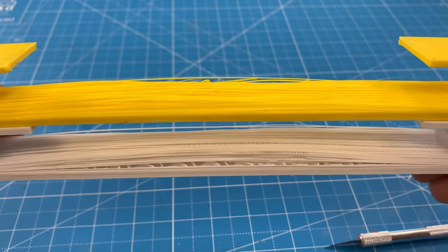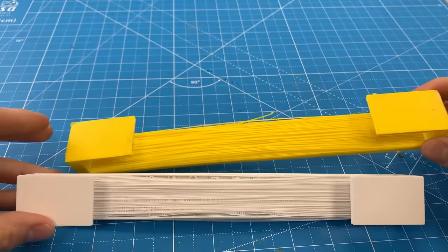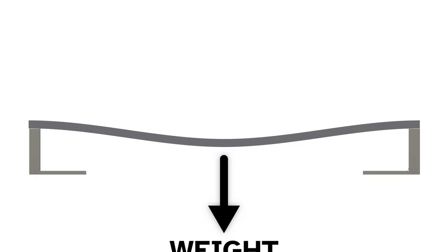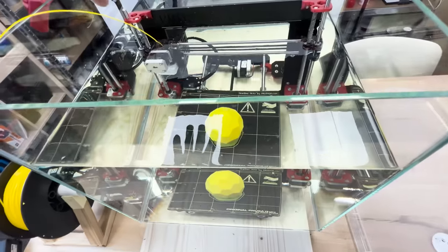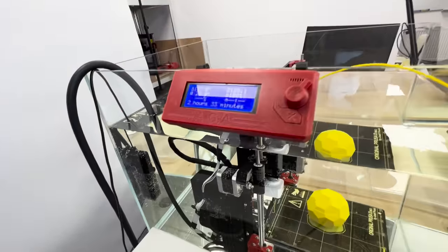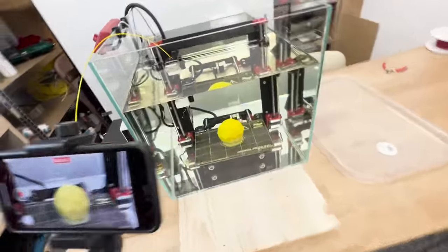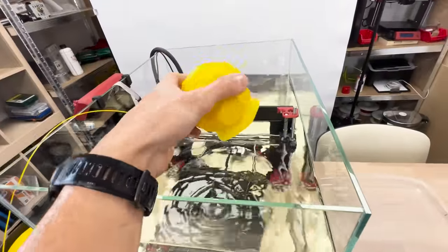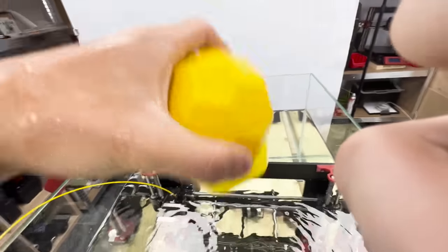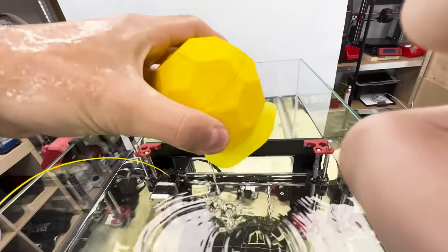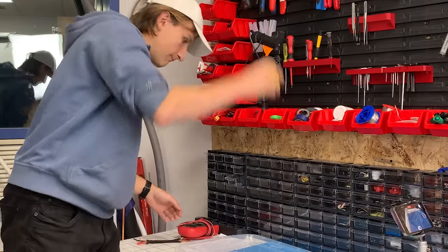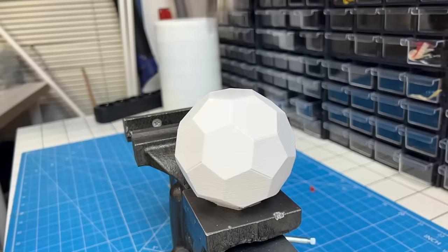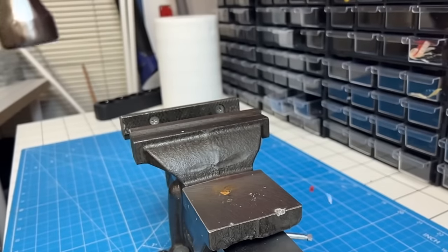Comparing the two prints together, they look very similar, but the one printed underwater is a little bit nicer in the overhang areas. I think that in this print, it's not better cooling that helped to achieve a better result. It's actually the fact that plastic in the water is much more buoyant than in the air, so each piece of plastic is effectively lighter. Hence, the bridge sagged down less when it was printed underwater. Oh, and there's also one more feature of underwater 3D printing. It's heavy. You can't really hear the water inside, just because there's no air inside. The prints are full of water, unlike the non-underwater prints.